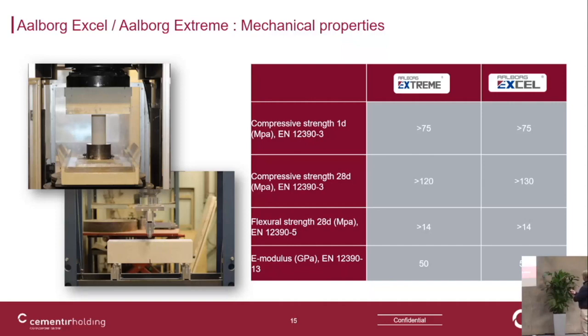After 28 days, a slight difference between Aalborg Extreme 120 MPa characteristic and 130 for the Aalborg Excel. And then the flexural strength is, of course, depending a lot on the fibers you use. But even without fibers, we have already a flexural strength of 14 MPa. And the E modulus is around 50 gigapascal.